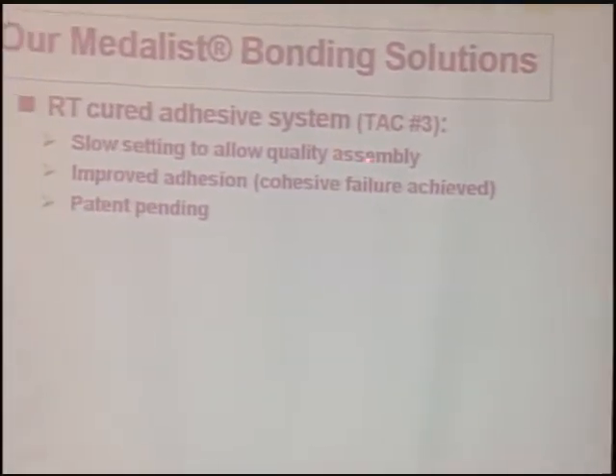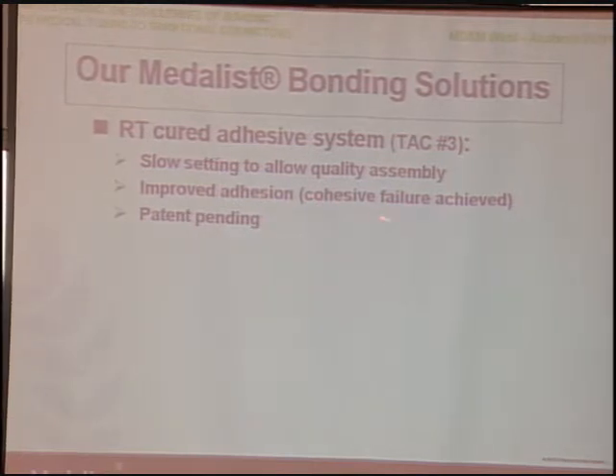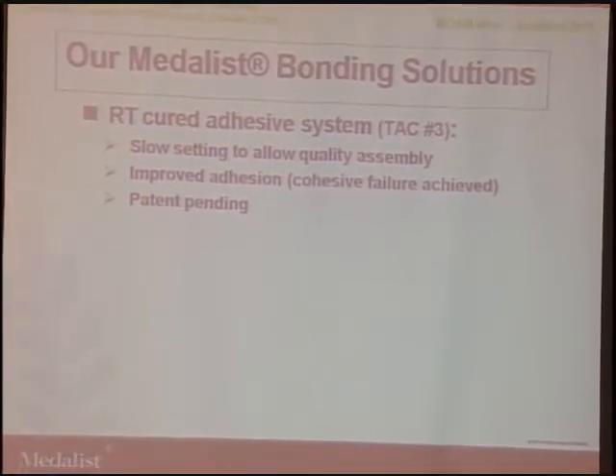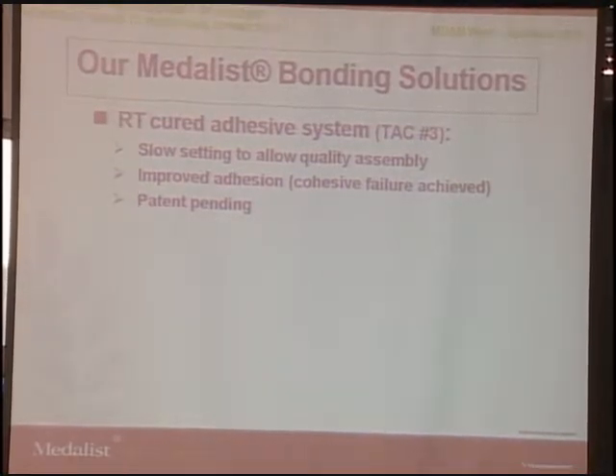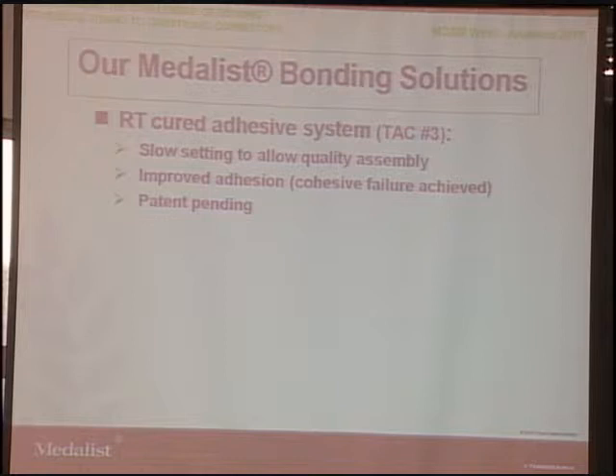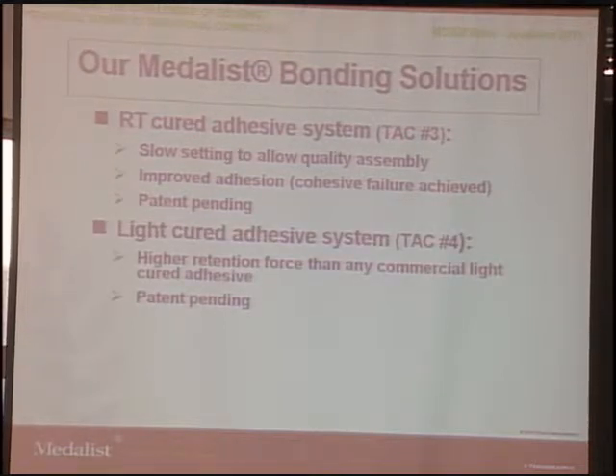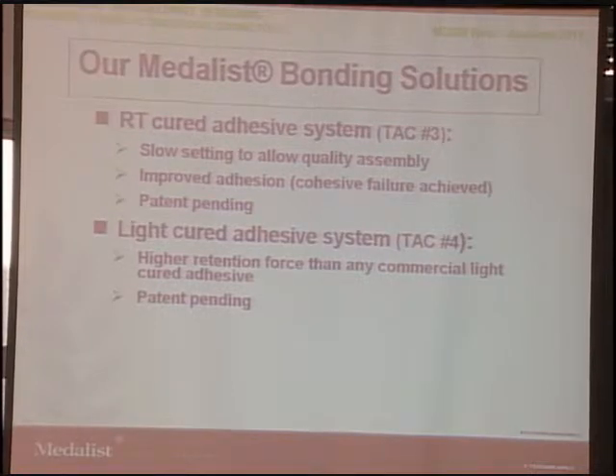Now the good news is we have the solution that people are looking for. For room temperature, we have a room temperature cured adhesive that significantly improves the adhesion. In fact, this room temperature cured adhesive system we commonly refer to as TAC 3. It can lead you to cohesive failure, which means when you pull the tubing from the connector, the tubing breaks rather than the tubing pulls out. We also developed a light cured adhesive system we refer to as TAC 4, and the retention force is higher than any other commercial light cured adhesive.